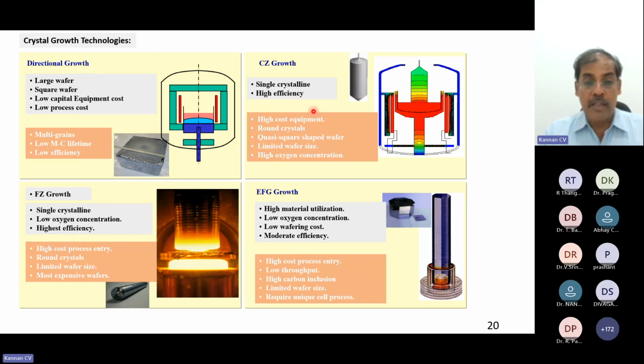That's the reason, as I said, there is another, float zone technique, where there is no crucible, whereas in silicon here, crucibles are used. So all the molten polysilicon is in contact with the crucible. Crucibles are not very high pure, whereas the raw material is very high pure. So there is contamination from crucible to the melt, so that contamination will go into the crystal also. Whereas in the float zone, there is no crucible. So the rod is melting and converted into the crystal. That is the reason the purity of the float zone method is very, very high compared with other techniques.